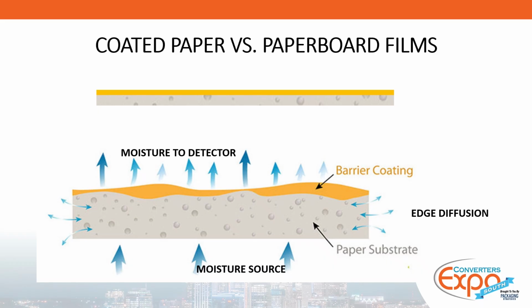And this is the mechanism that was going on as to why the much thicker substrates had what appeared to be a much better barrier and a much lower water vapor transmission rate. That's because versus what you see on the top there, a much thinner substrate, you don't have all this increased surface area that is now available for your moisture to move laterally, because diffusion is non-directional. The molecules are just going to spread wherever they're going to spread. Nature takes the path of least resistance.